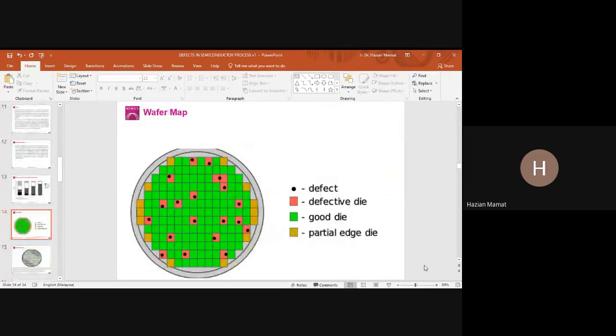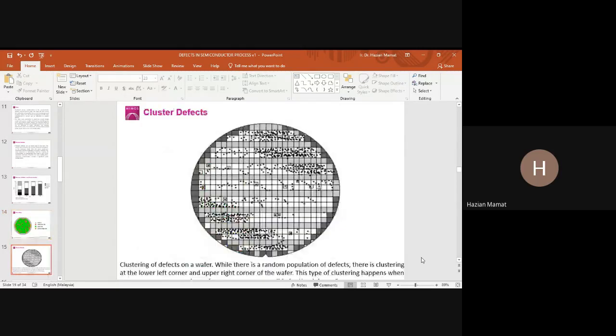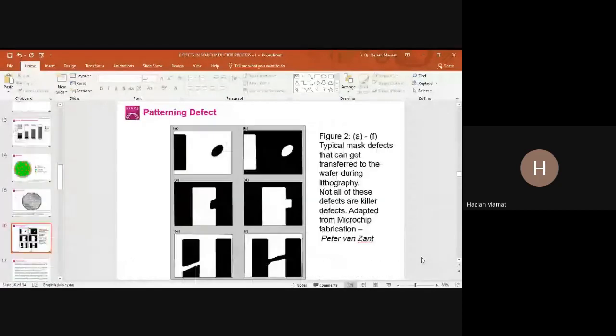Okay, this is the wafer map, for example, to show you that a defect may happen anywhere in the wafer. It's not only on one die. It may affect the surrounding chips. Okay, and this is the cluster defect, where you can see there is a defect on the bottom and also on the upper level. This is an example of a patterning defect, which comes from the lithography process. Not all of these defects are killer defects, but they may affect some of the function of the microchip.